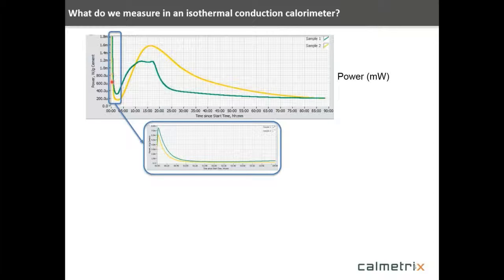And you see here as that reaction gets damped down and then we come into the dormant phase for the cement. So all this happens very early on, and depending on the type of reaction that happens, you have more or less time associated with the dormant phase before the main reaction then starts to kick off.